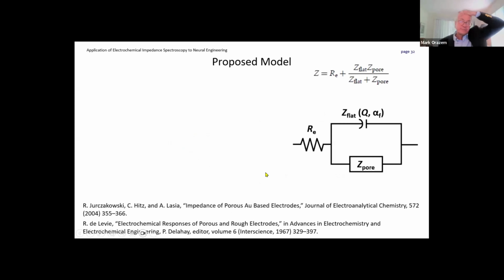So the proposed model, we have a porous electrode. With deep pores, we have to account for the porous electrode model. But we have a distribution of pore sizes, and so the part of the system with shallow pores really starts looking like a rough, flat electrode. So we have a flat electrode that is in parallel to the porous electrode. And this model was also proposed by Lasia's group for porous gold electrodes. And we have an ohmic resistance that is in series with all of this.